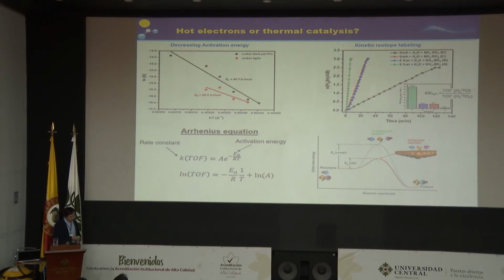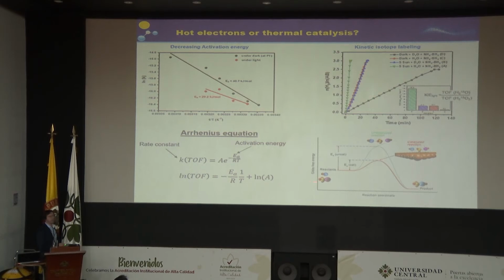And of course this can come from the much more efficient absorption of light in titanium nitride, but also the difference in, for example, carrier density inside the materials. And this is important because electron scattering, so energy dissipation of hot electrons, can be limited if you have fewer carriers inside the materials. And so finally, this is just the picture of what I was saying before.